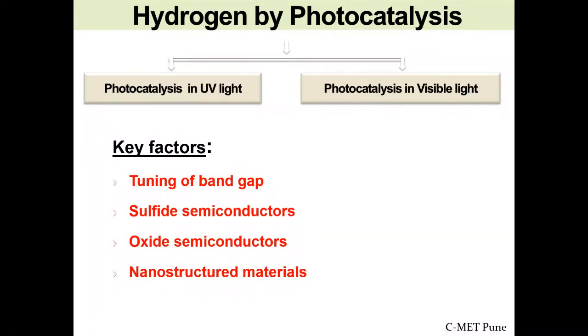What we have to do here is, we have photocatalysis by UV light and photocatalysis in visible light. Visible light means your band gap should be in the visible region, almost 2.4 electron volts. Means your material should absorb sunlight from 400 nanometers to almost 600 nanometers. That is the visible region. So we need to tune the band gap of the material from 2.8 electron volts to 2.0 electron volts, so that we get more electrons and holes through this process.